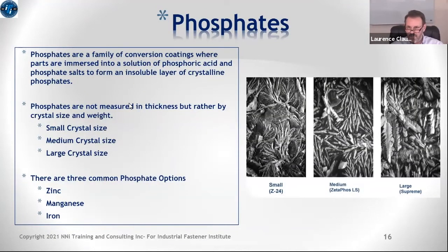All right, phosphates, moving right along here. Phosphates are essentially crystals. They're somewhat unique among all these different options that I'm going to show, because unlike any of the other finishes, which basically deposit a noticeable thickness on the surface of the part, phosphates don't. Phosphates create what's called a conversion coating when you immerse them in a bath of heated phosphoric acid and phosphate salts. The result is that you come out with this conversion coating on top that is basically a set of crystals, crystal phosphates. You see pictures on this slide of some examples of those crystals on the right-hand side, illustrating the difference between small, medium, and large size crystals.